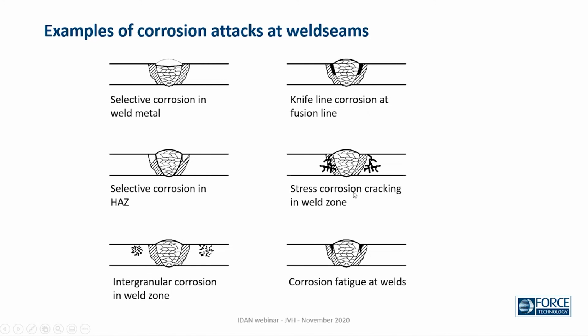Or we could have stress corrosion cracking from the residual stresses, and perhaps also when you have this cap on the weld, you would get some stress concentrations along the top, and by that increase the stresses and the risk of stress corrosion cracking. And for the same reason with the stress concentrations, we would also see that corrosion fatigue could attack along the welds. It's ordinary fatigue, but with increased sensitivity and growth rate due to corrosion.